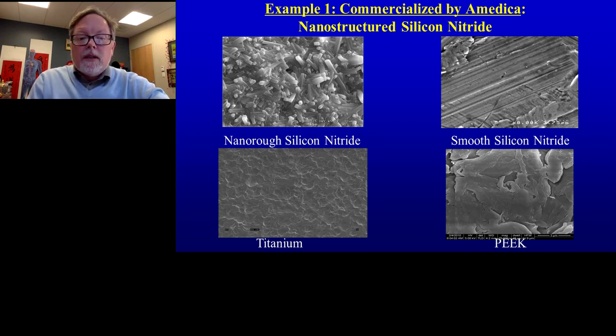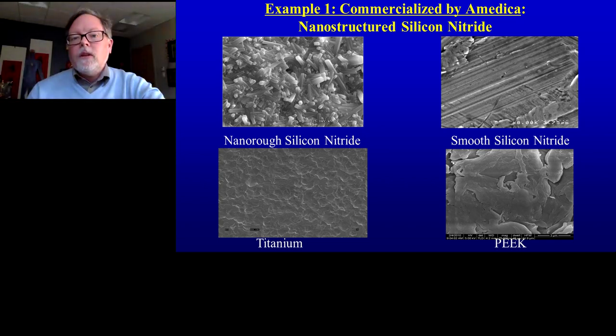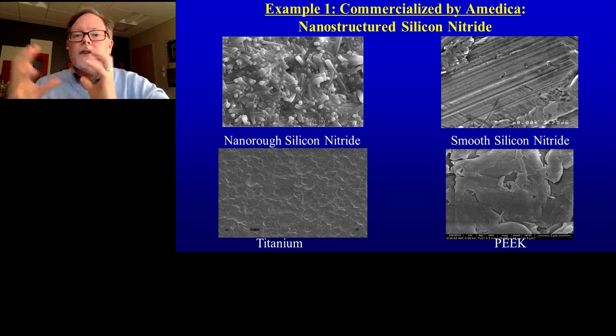We also compared this to titanium. Titanium, of course, as I mentioned, is a widely popular material in orthopedics. And we also compared it to a polymer called PEEK, or polyether ether ketone. Polyether ether ketone is the #1 implanted spinal implant material. So it has great mechanical properties. It has a really nice behavior for mechanical situations in the spine. Unfortunately, there's a lot of infection that occurs for PEEK because it does not resist bacteria growth.